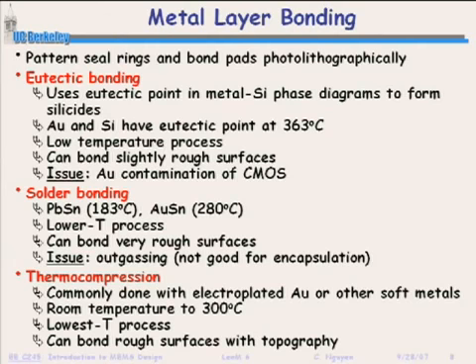Gold and silicon have a eutectic point at 363 degrees C. So the temperatures are very reasonable, quite low here. It's a low temperature process, and you can bond slightly rough surfaces. For CMOS integrated circuits, there's an issue with gold contamination. And usually gold and silicon is the type of eutectic bonding people try to do in these sorts of things. I'll also warn you that this suffers from uniformity issues.